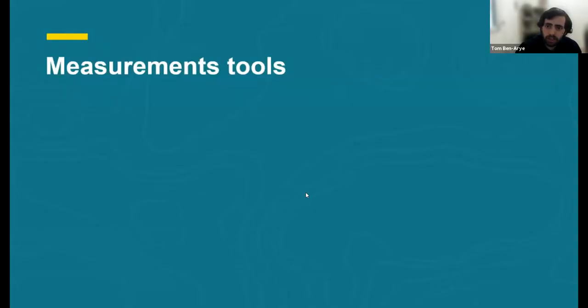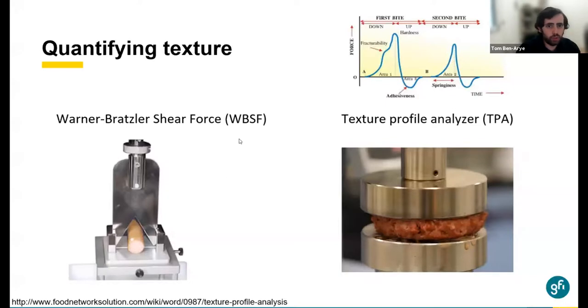When we want to quantify the success of our experiments, we want to quantify novel traits, but we use some measurement tools that are common in the tissue engineering area. However, we want to also measure additional parameters. For example, for quantifying texture, we can use a texture measurement such as WBSF or TPA. I would mention that WBSF basically has this structure. It goes down and tries to cut the sample and measure the forces in order to quantify the texture. In the texture profile analyzer, this technique tries to mimic two bites into a sample, as you can see here in this graph, and measures the forces during that.